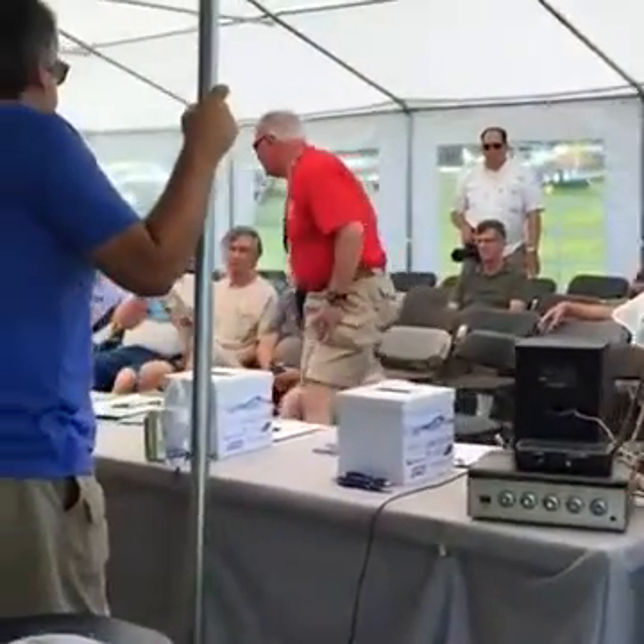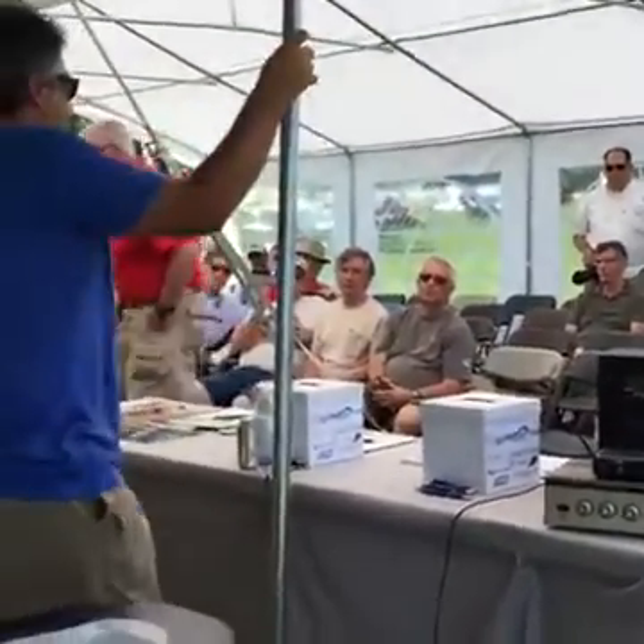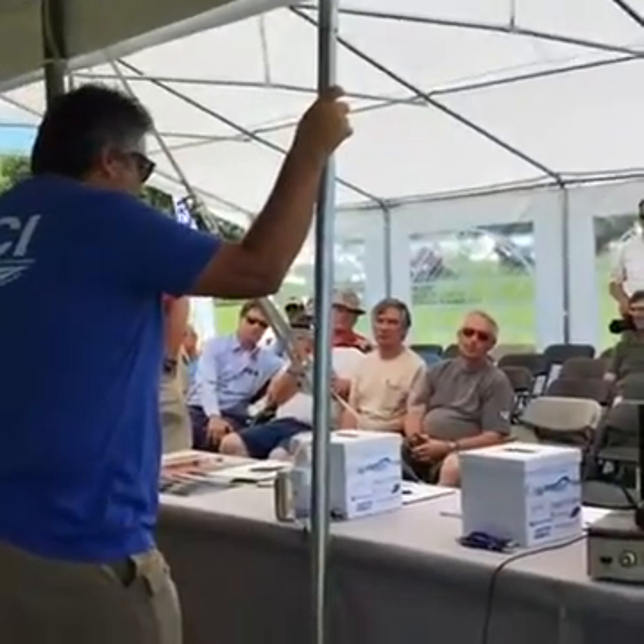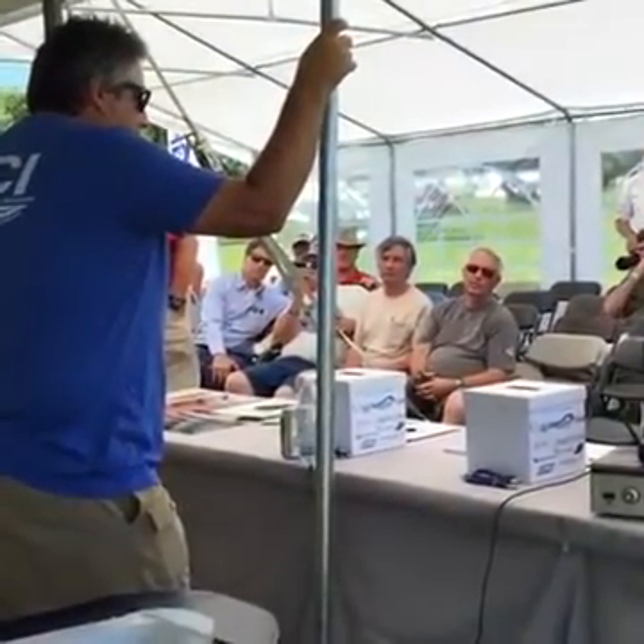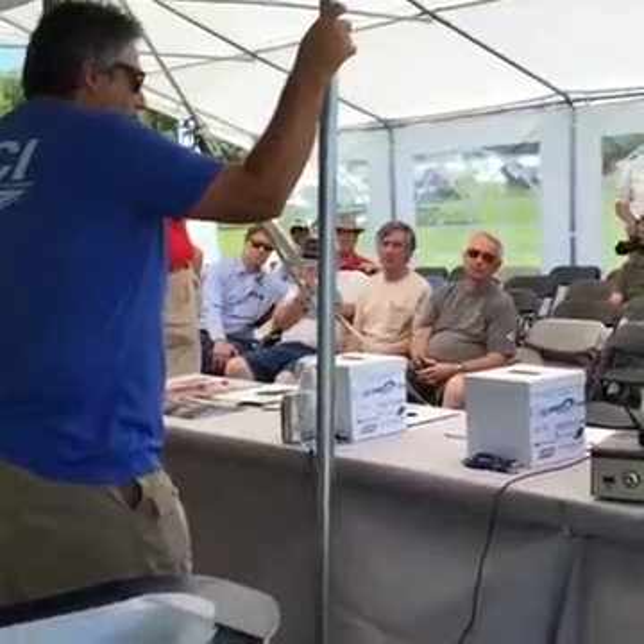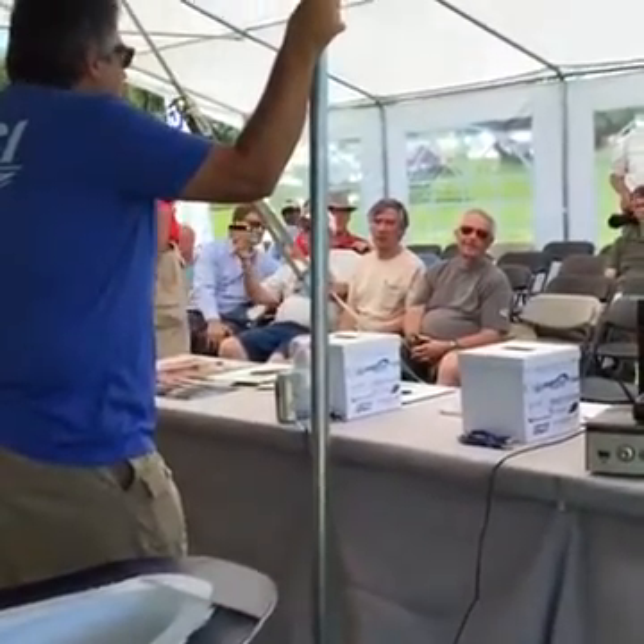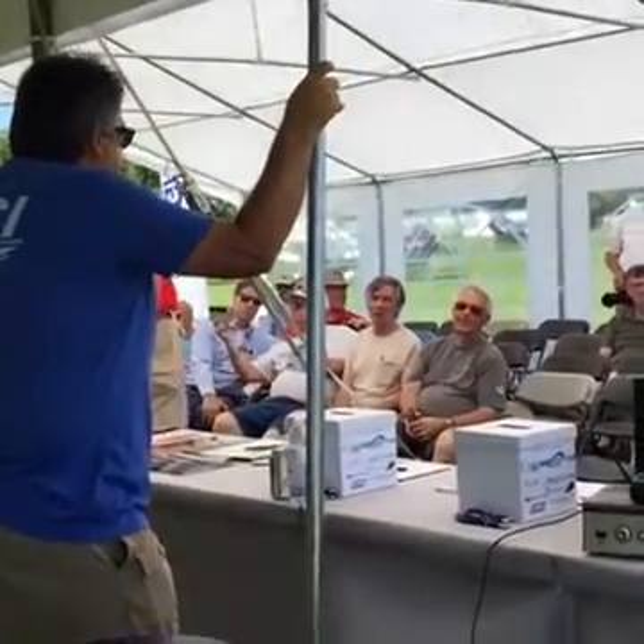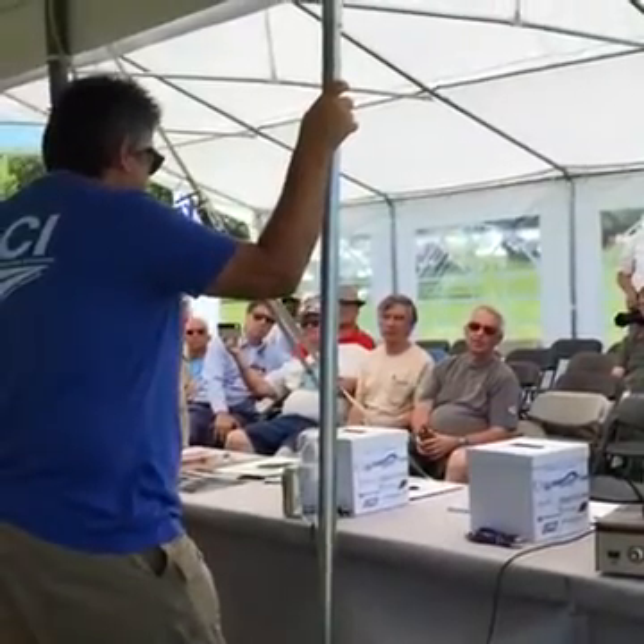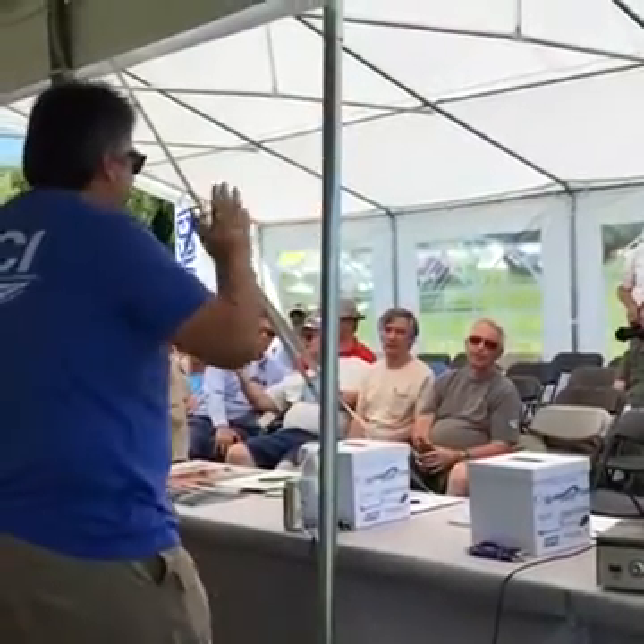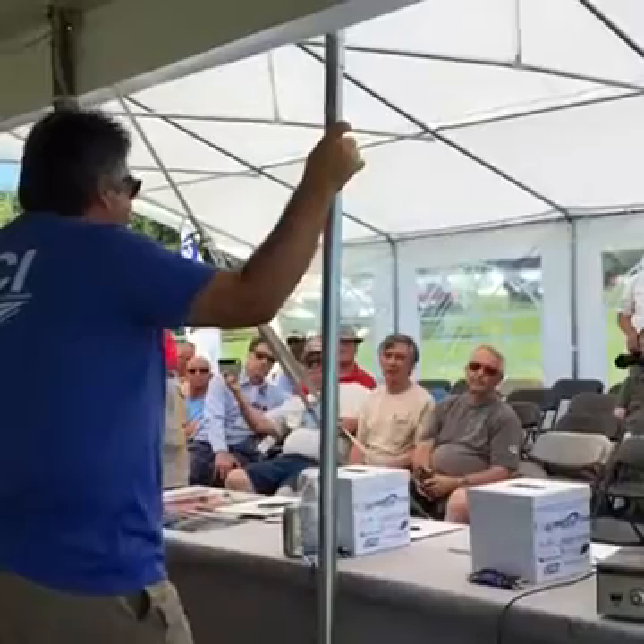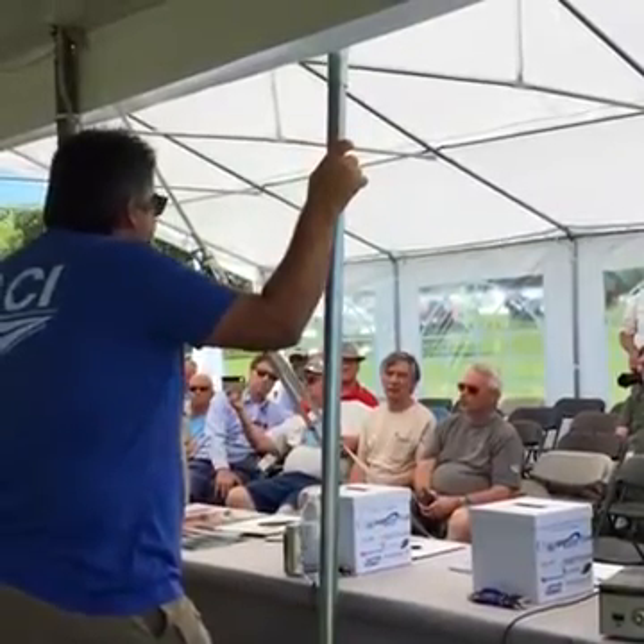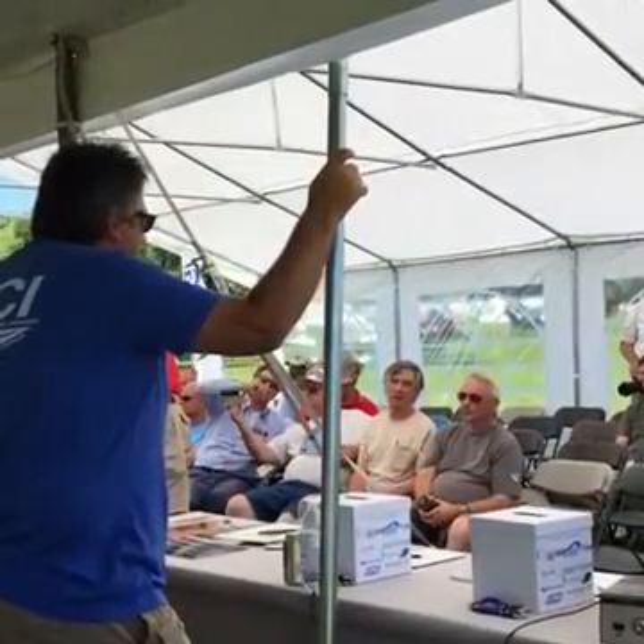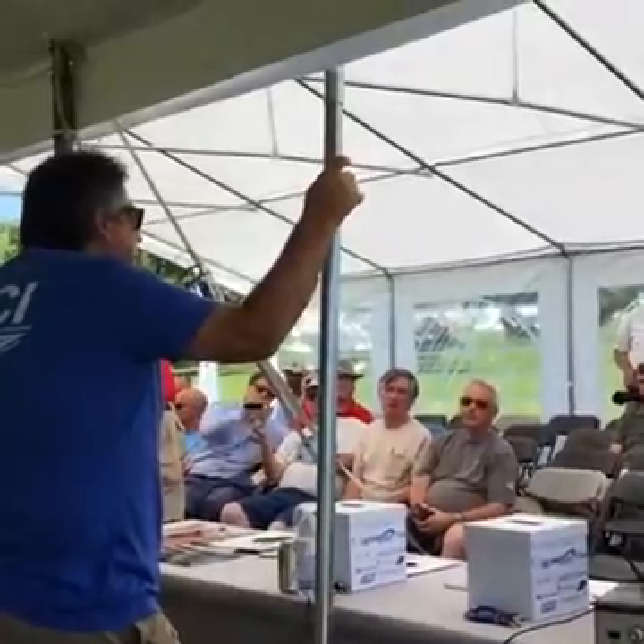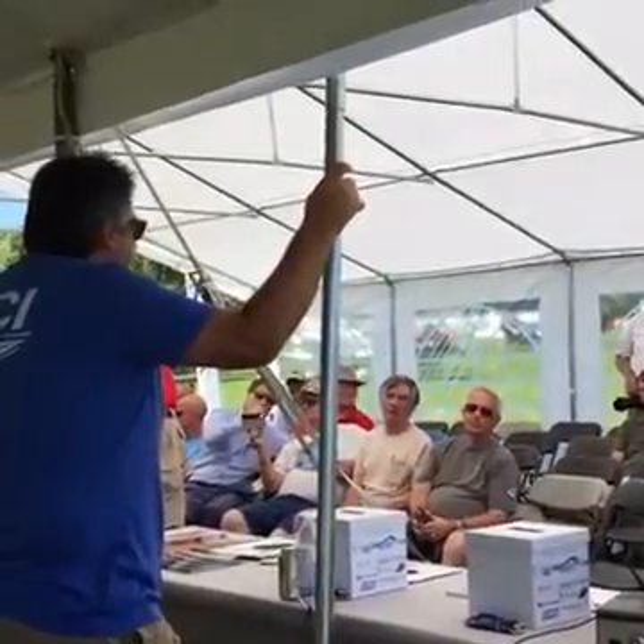We do better in UV. We do better in moisture absorption. We do worse in, I think, which ones do we do worse in? How about peel strength? Peel strength is always the hardest part for any resin to go through because it's not made to peel just like an adhesive. But it's equivalent to a vinyl ester, maybe about 92% of what an epoxy would do.